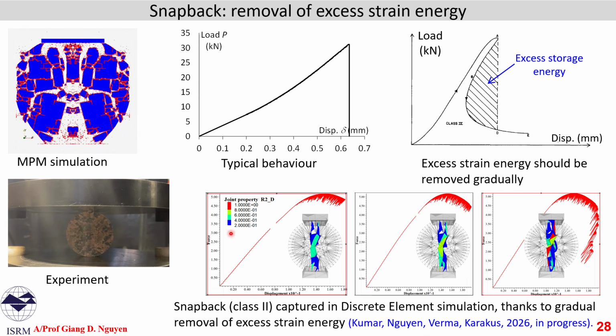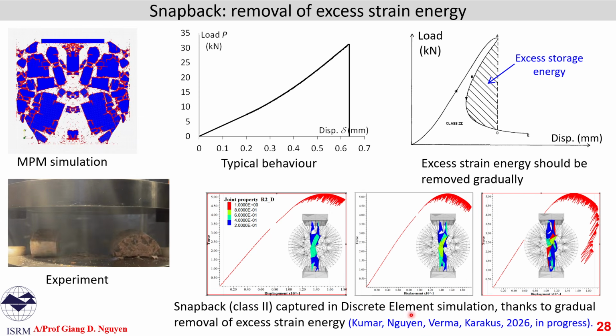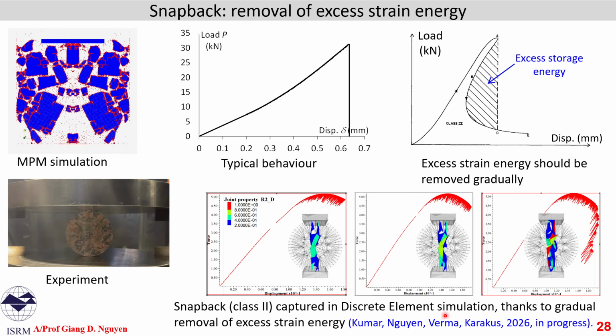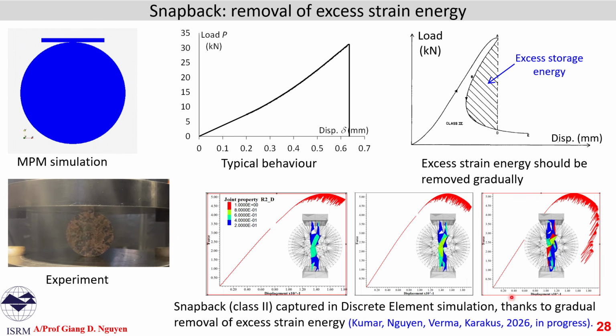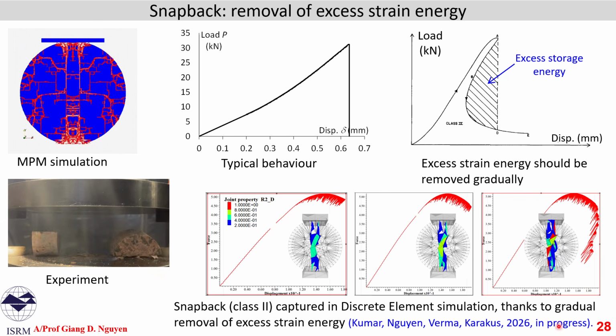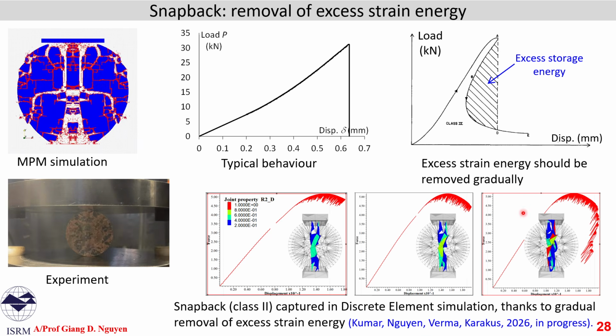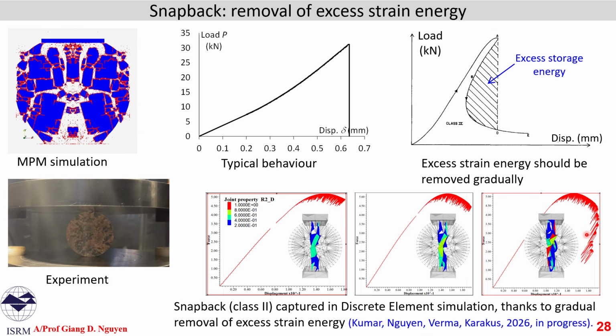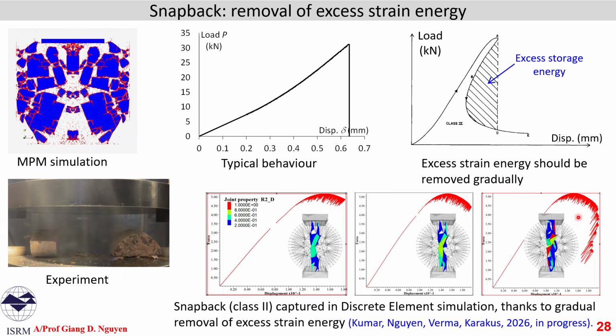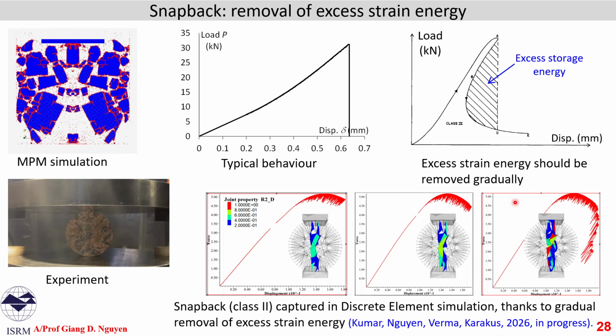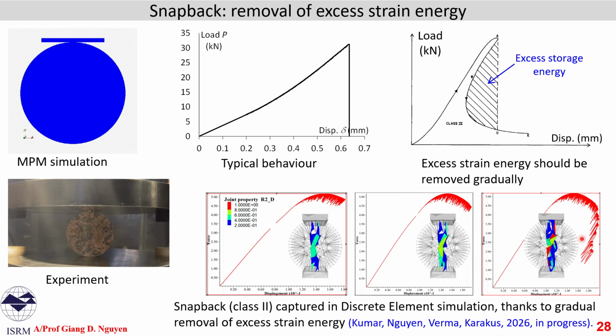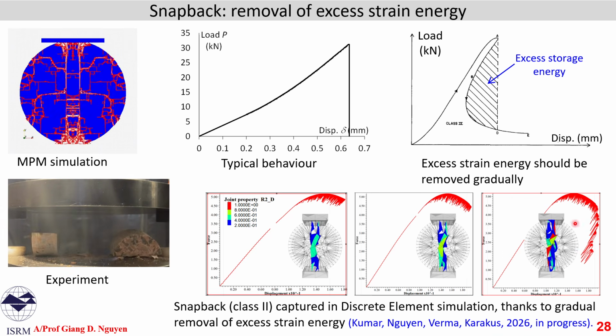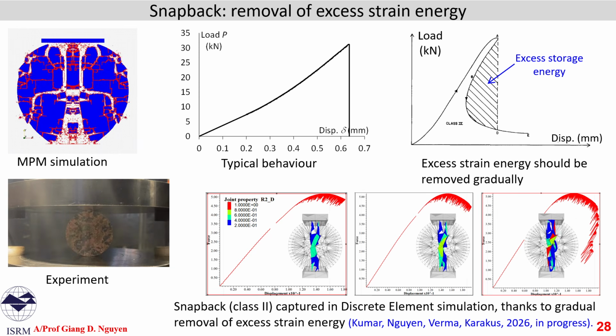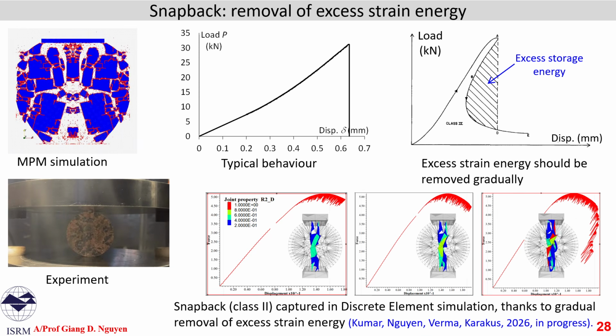We had some successful simulation here using the discrete element method, 3D in this case, but this is still a work in progress. And we apply the same principle, the gradual removal of strain energy here, to capture the snapback process and stabilize the fracture process. In this case, Brazilian disc.